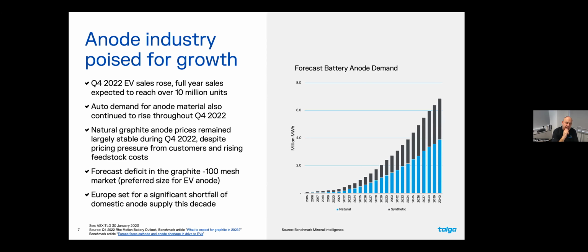EV sales are now kicking in harder. Battery cell demand is kicking in harder. There's been a lot of flexibility with different sources of graphite, both synthetic or artificial and natural, that have been able to get scooped up. And now you're seeing places like China become a net importer for the first time of natural graphite. The preferred size for making anodes is quite small. Anode particles for batteries are actually very small. They range from 5-6 micron up to just under 20 micron. But the trend is towards the smaller sizes for faster charge kinetics and things like that. So around 10 micron or less is premium sort of products.